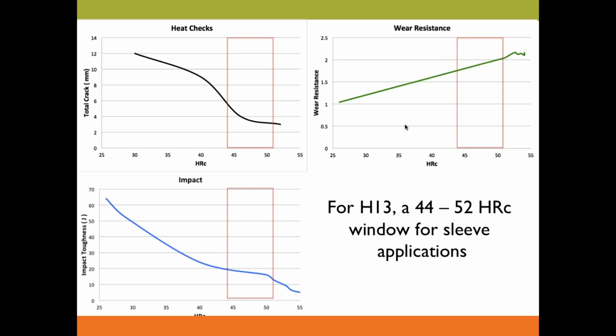I mean, the shorter the total crack length, the better the heat check resistance. But they are not linear. You can see it goes from 30 to maybe 40, kind of linear, but all of a sudden it becomes better from 40 to 50. And for the toughness, it drops quickly from 30 to 40, and from 45 to 50 it plateaus out. So for most short sleeve applications, H13, the window from 44 to maybe 50 or 52 Rockwell is a good window to start with. And then you can start to tweak around. Let's say if you want a higher wear resistance, you can increase the Rockwell.